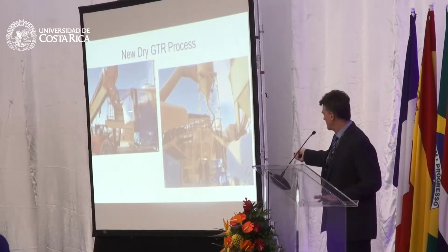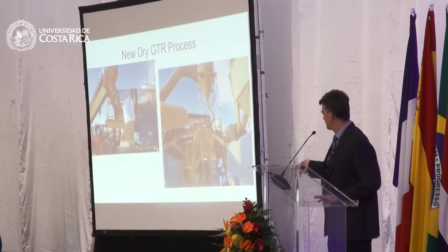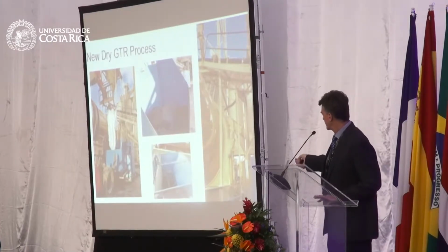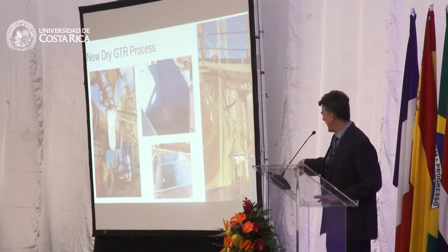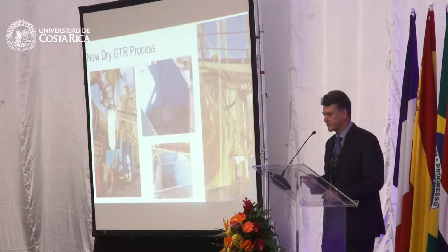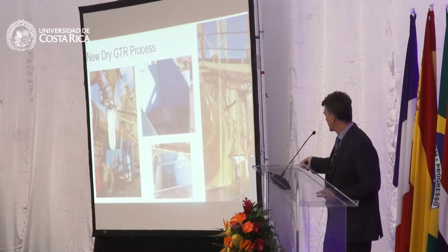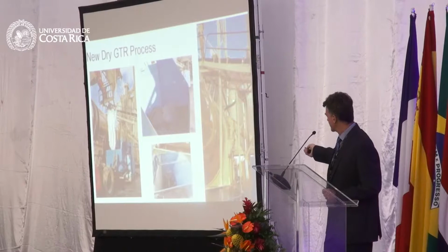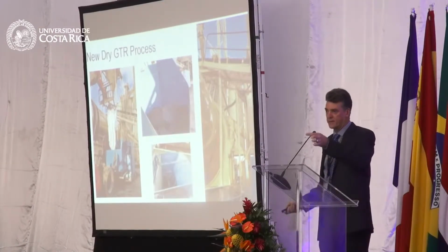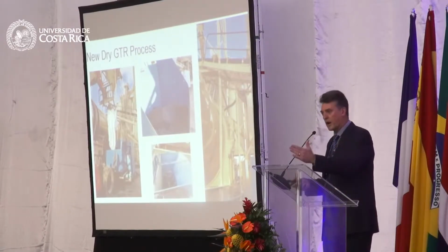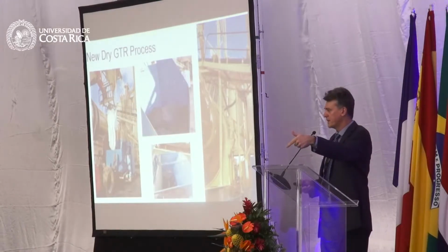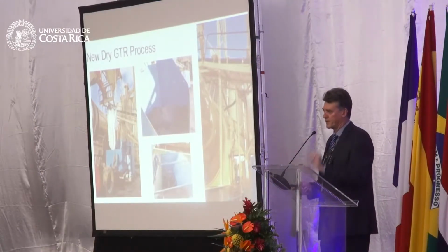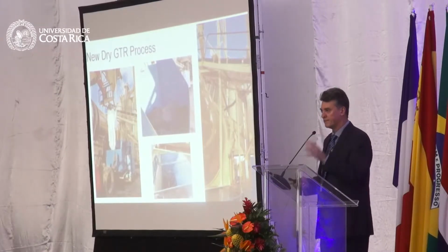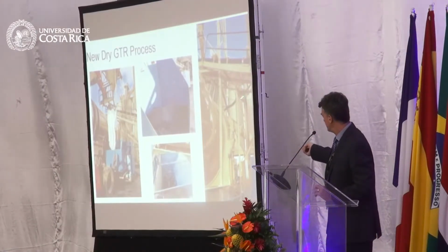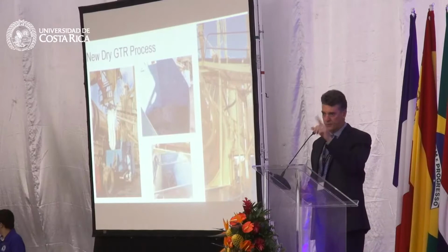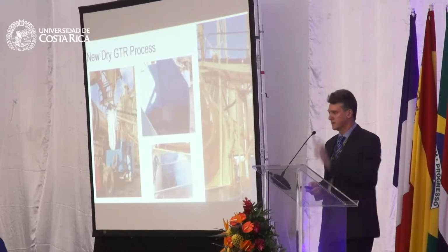You have these large totes that are dropped into this fiber unit. You can see there's paddles down here, so it's like a pug mill mixer. It just breaks up the ground tire rubber. And then it's hard to see in this picture, but there's a tube that goes into the place in the drum towards the bottom where the recycled asphalt goes in. In that same location at the bottom third of the drum is where you blow in, pneumatically meter in the rubber. So you can watch the rubber flowing through the tube. It's a clear pipe.